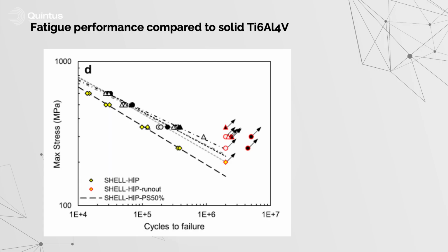So I'm focusing my research on improving structural integrity, and that's why I work with some researchers on fatigue properties, and HIPping is a key to structural integrity in additive. This canning or shell HIP combination process that we've been discussing improves the speed of manufacturing, and there are even some structural integrity advantages compared to traditional methods because there's less thermal buildup. Because only a shell is being built, you don't have so much residual stress, and you don't have the possibility for residual stress induced cracking.